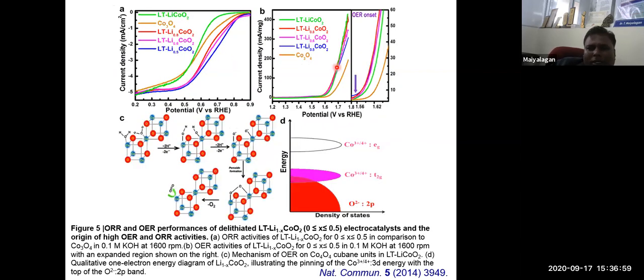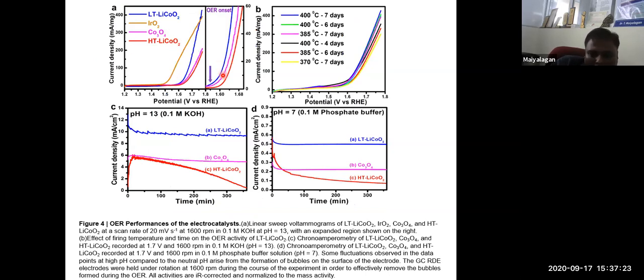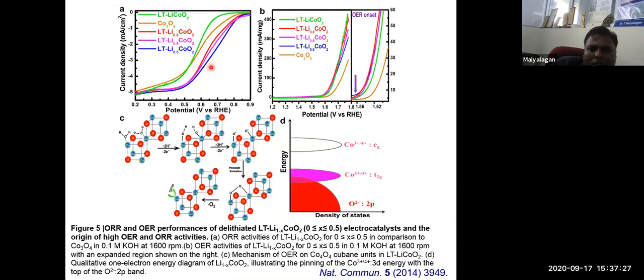So when you look at this catalyst, I want to say that in the air battery, you need both oxygen reduction and oxygen evolution reactions to take place. So what we need is a better oxygen evolution reaction in the air battery. So I chose a material, lithium cobalt oxide, for the oxygen evolution reaction. I got better performance than iridium oxide. Now I want to test the same to replace the platinum. So the idea of the study is to replace platinum and iridium oxide.